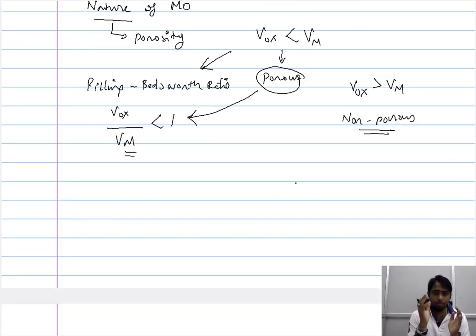The way the porosity relates to understanding the rate of oxidation is because in highly porous oxide layers, it is the mobility of the ions that ultimately governs the rate of oxidation. Again, the rate of oxidation we treated in the theoretical framework as the increase in the thickness of the existing layer of metal oxide. To increase the thickness of the existing layer, you need to have propagation of ions. This can be either the propagation of the metallic ion or the oxygen ion. So when you have a medium that allows a high degree of propagation of these ions, the rate of oxidation is enhanced. The rate at which the thickness grows is enhanced.